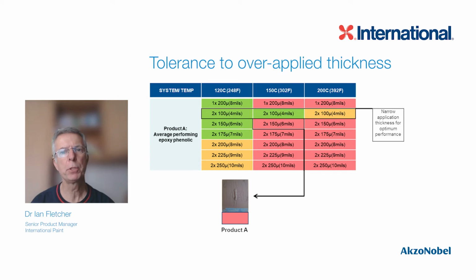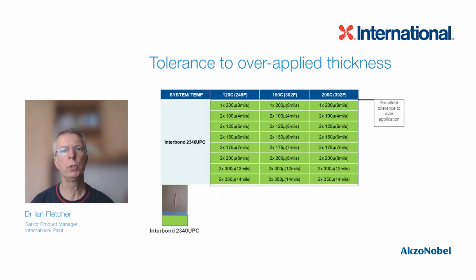What we found was that for some temperatures and film thicknesses, a traditional epoxy phenolic performed well, but as the film thickness and temperature increased, cracks started to form. The overall conclusion was that to get the temperature performance expected, a very narrow dry film thickness range of 2 times 100 microns was necessary, and even then it cracked at 200 degrees Celsius. When we compared Interbond 2340 UPC's performance in the same test, we found that it performed very well across a wide range of coating thicknesses and temperatures. Interbond 2340 UPC, being a next generation epoxy phenolic, has greater film flexibility compared to traditional epoxy phenolics, and this allows it to withstand over-application so much better.